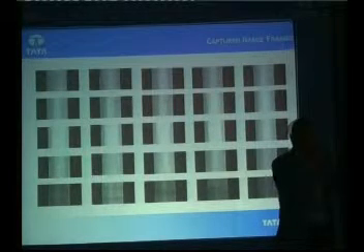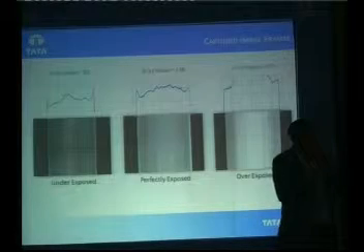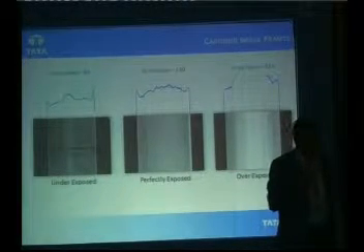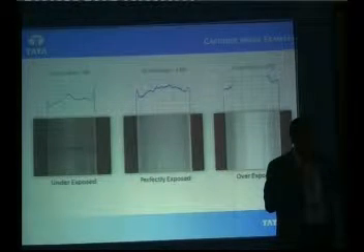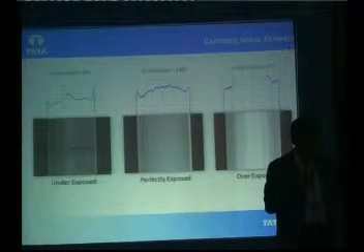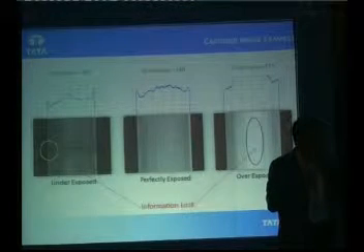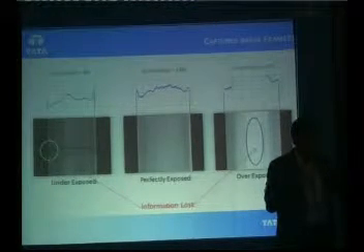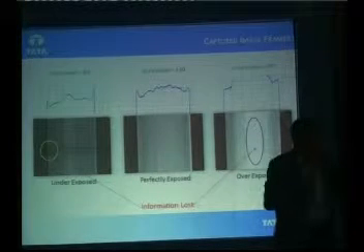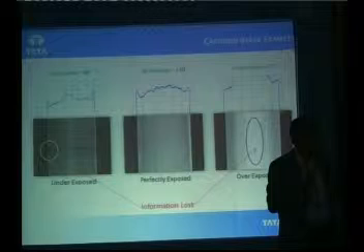Now, we thought that this was the end of the implementation, but then we saw that defect detection efficiency is sometimes very good and sometimes not so good. So why? We thought about it and got the answer. We captured several images over several months and saw there is a drift in the gray level of the images. Some images are underexposed, some are overexposed, and some are perfectly exposed. During underexposure and overexposure, image information is lost. The optimum gray value we found for perfect exposure is 130.